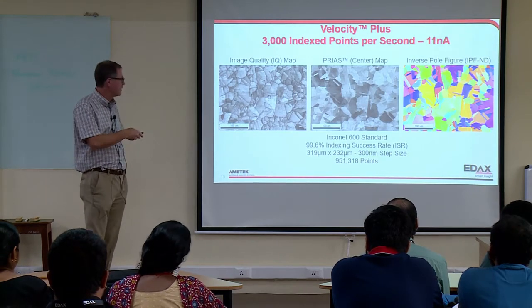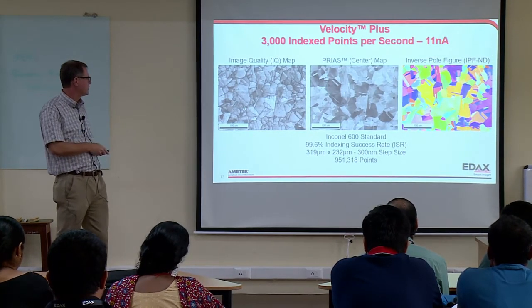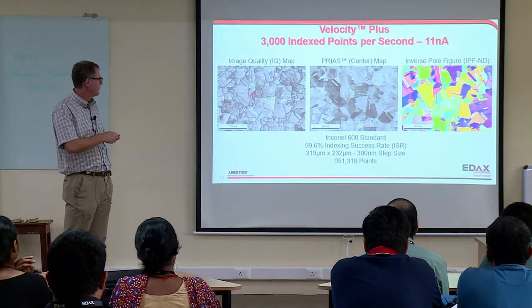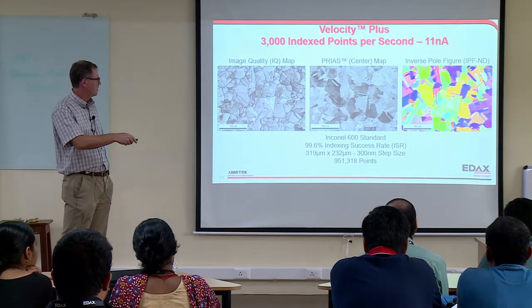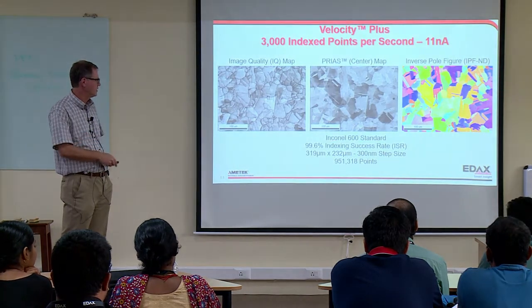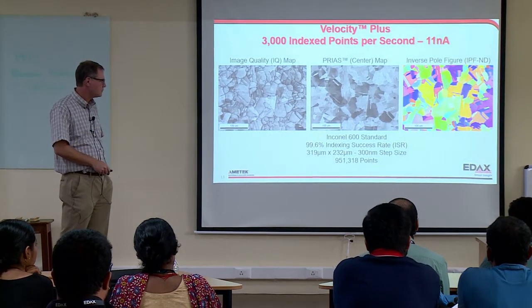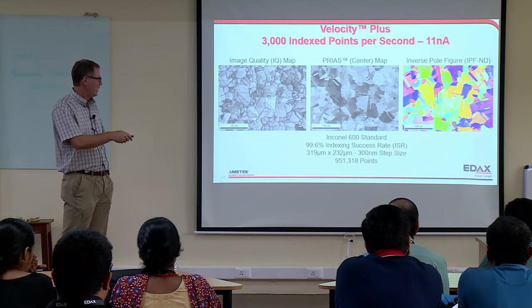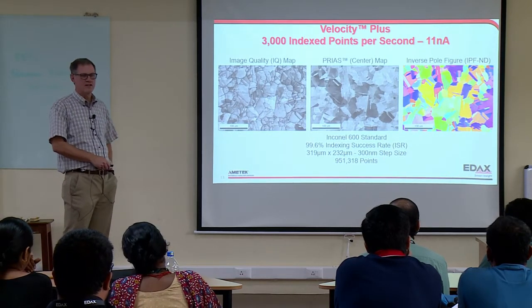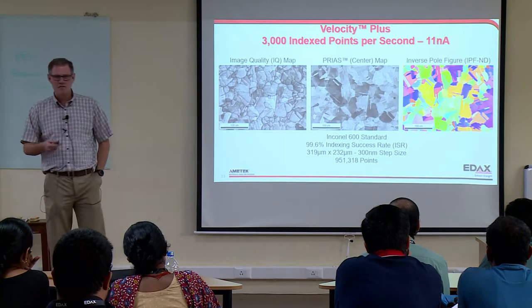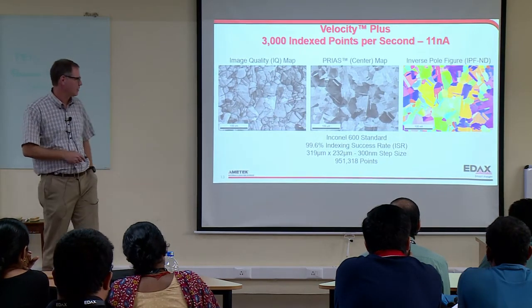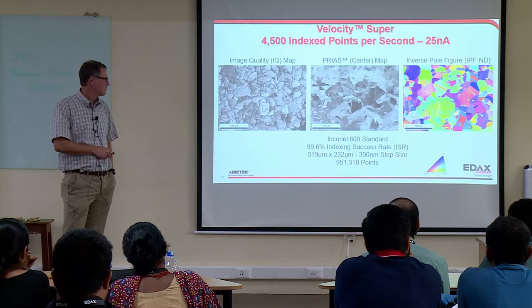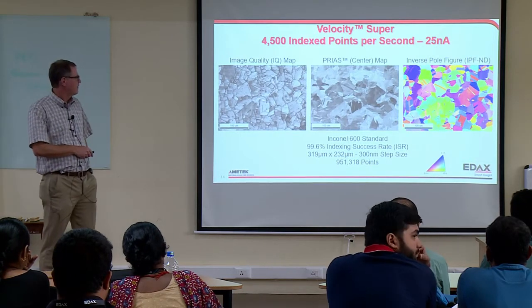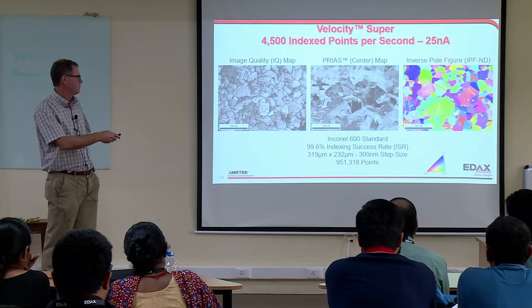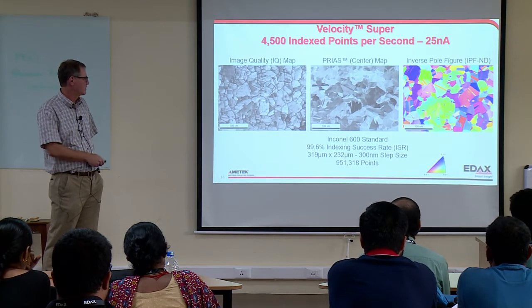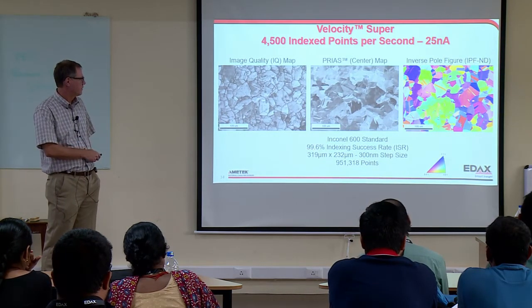And this is just an example. This is 3,000 index points per second at 11 nanoamps. Here's the IQ map and inverse pole figure. You can see we're getting great indexing, basically 100%, really rapidly. And the challenge now is we're collecting so much data that we're having to rethink some of our analysis routines, because the amount of data we're collecting is so much more than we're used to. This is at 4,500 points per second, and you can see there's no change. It's still perfect indexing, basically 100%.